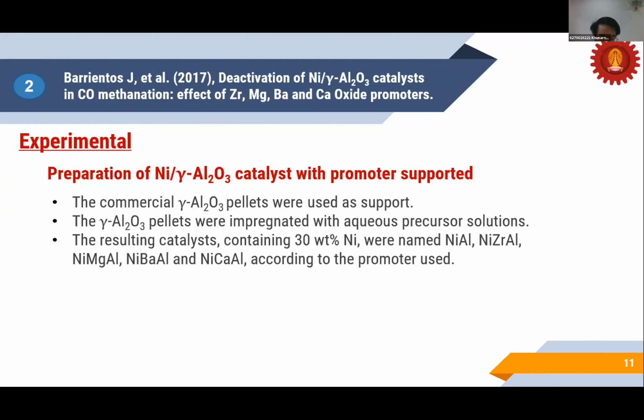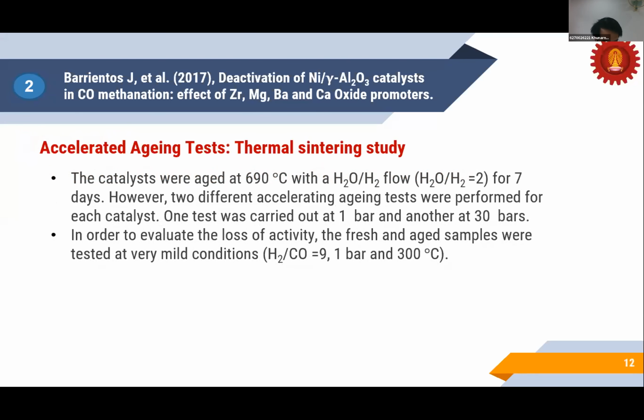The second paper is deactivation of nickel on gamma alumina catalyst in CO methanation: effect of zirconium, magnesium, barium, calcium oxide promoter, published in 2017. The objective is to evaluate the effect of different structural promoters on thermal sintering under relevant methanation conditions. The resulting catalysts containing 30 weight% nickel were named according to the promoter used. This is the condition that accelerates the aging test, thermal sintering study.